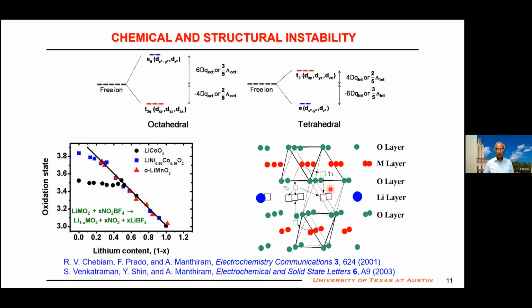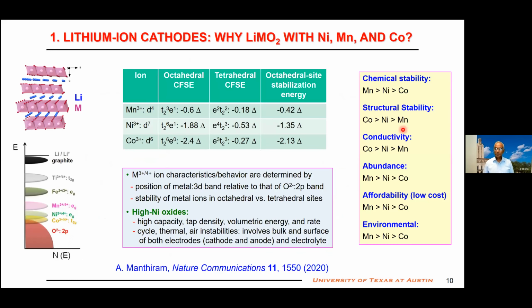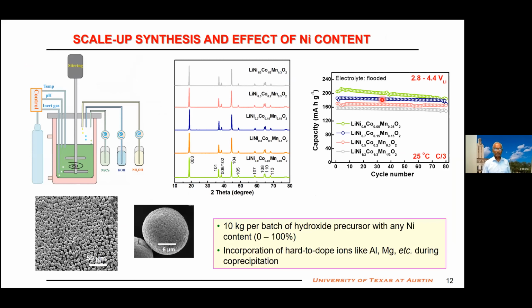So structural stability wise, cobalt is the best, manganese is the worst. So it's a trade-off with the cobalt because structural stability is always important. That's why the commercialization happened in 1990 by Sony with the lithium cobalt oxide. There are other criteria here. I won't have time, but you can see nickel is in between nicely in all of these criteria between manganese and cobalt. That's why everybody is on nickel now. So when you increase nickel, let me go back here.